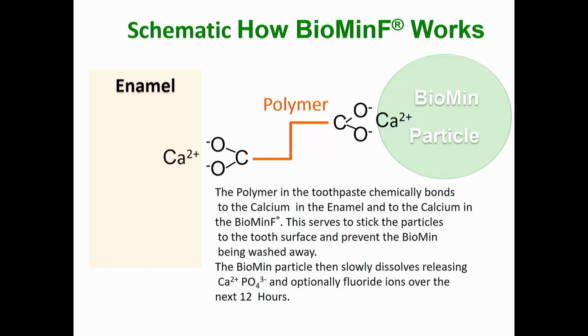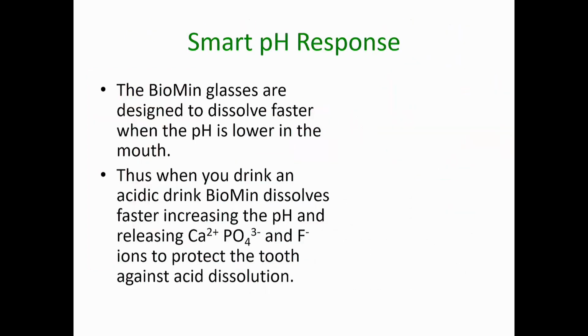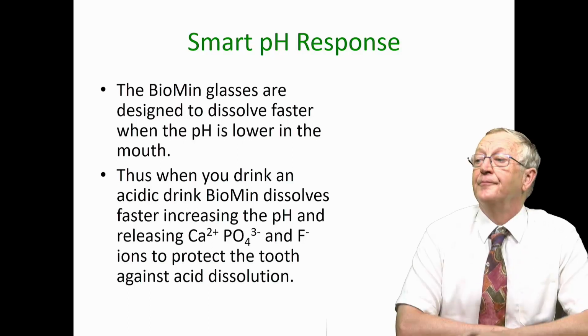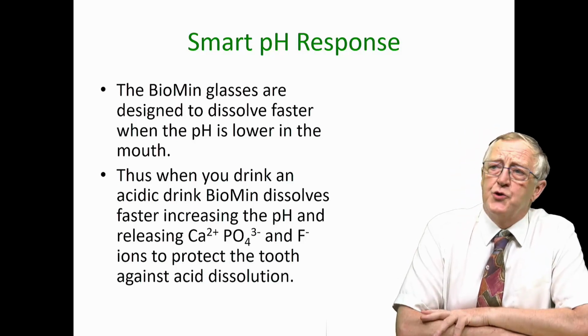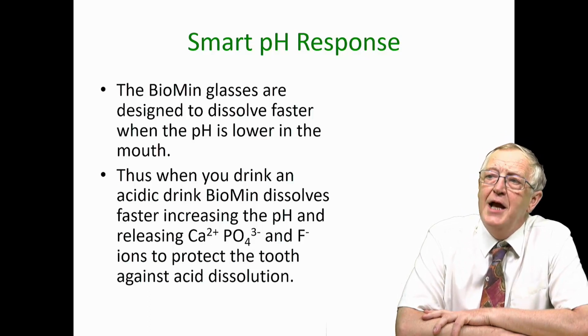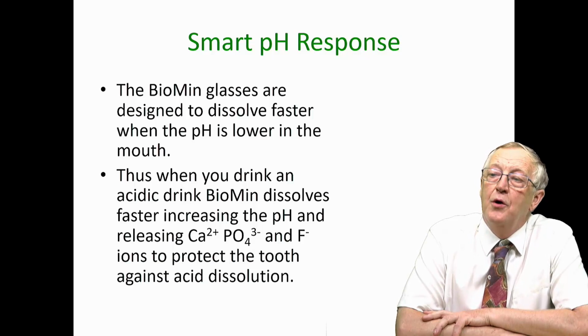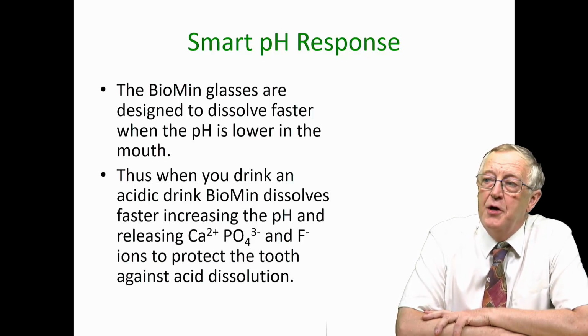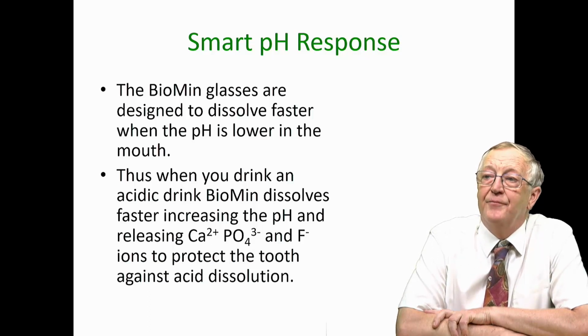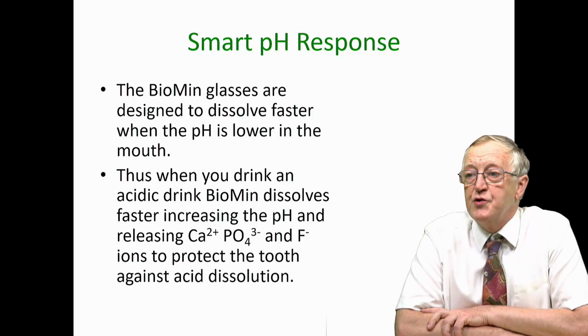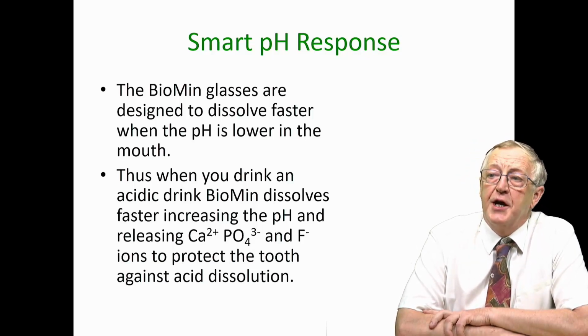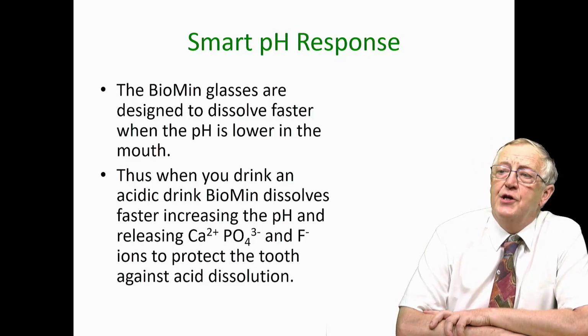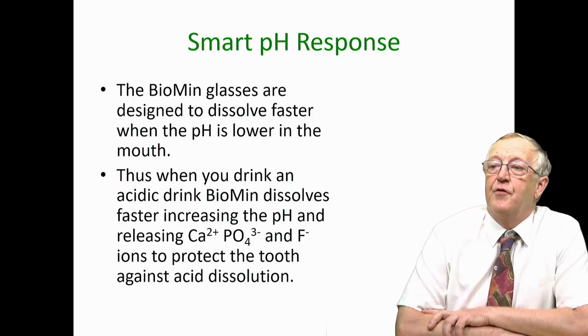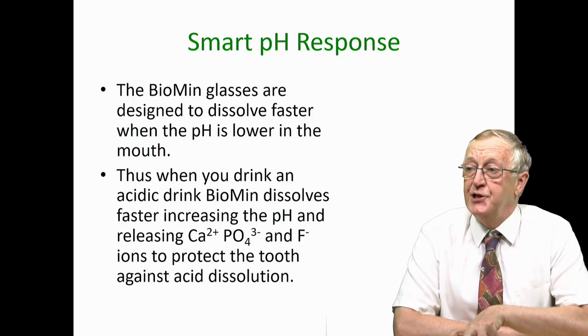The polymer in the toothpaste is the same polymer that's present in glass ionomer cements that provides the adhesion to the tooth structure. So the glass ionomer cements, of course, have polyacrylic acid in them too. The Biomin glasses are also designed so they dissolve faster when the pH is lower in the mouth. So the glass will dissolve about 10 times faster at pH 4 than it will at pH 7. And this is a very attractive, smart response of the glass, so that when you drink an acidic drink, the Biomin glass dissolves faster, increases the pH, and releases calcium, phosphate and fluoride ions to protect the tooth against acid dissolution.